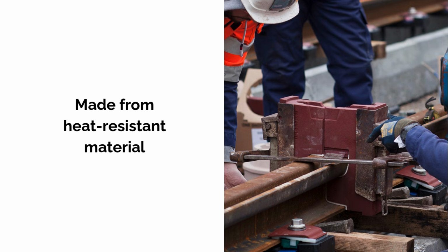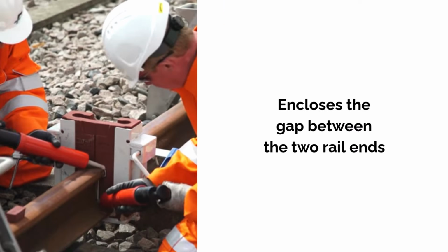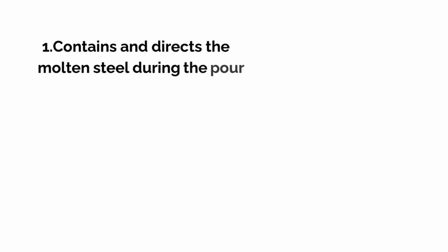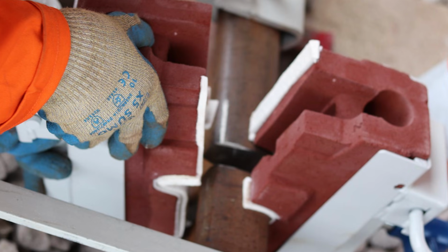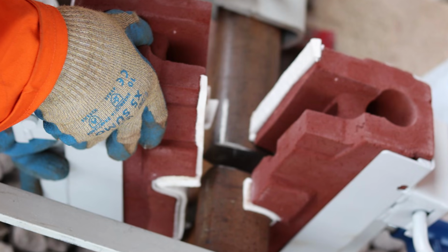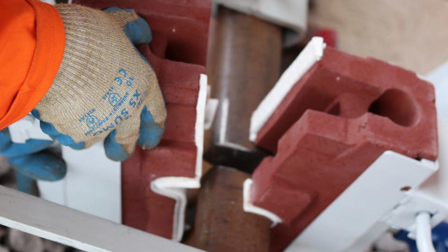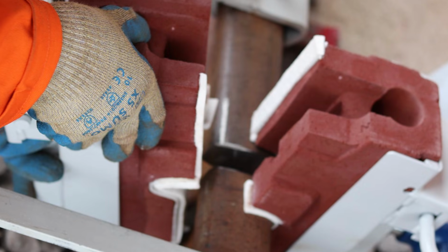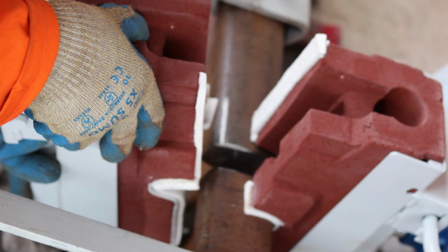The mould sits tightly around the rail head, web, and foot, enclosing the gap between the two rail ends. Its internal shape mirrors the rail profile, defining the form the weld will take once the metal solidifies and is ground back. The mould performs three critical functions. First, it contains and directs the molten steel during the pour. Internal channels guide the metal into the joint from the bottom up, allowing air and slag to rise away from the running surface rather than becoming trapped inside the weld.